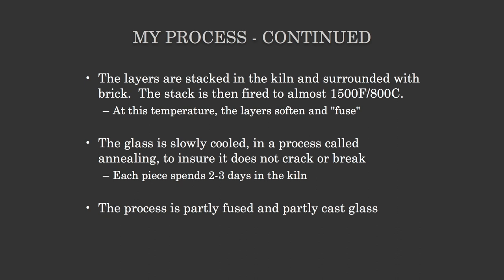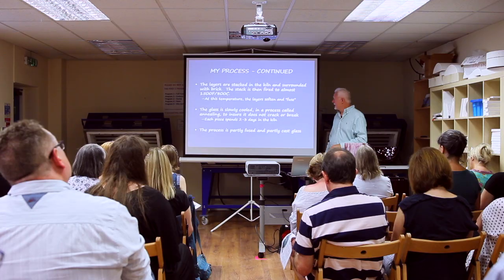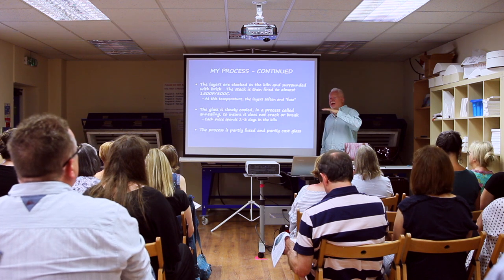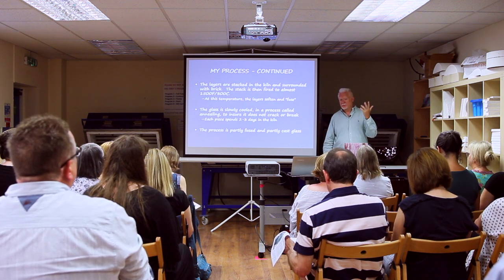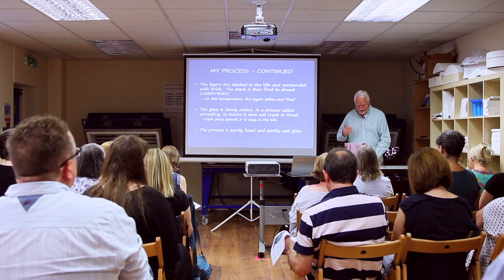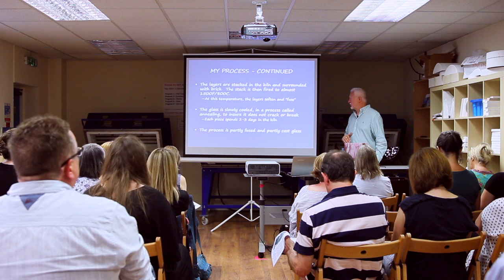Because at this point, I heat it up to 800 degrees Celsius, and at that point, the glass melts to the consistency of honey. It's a very thick liquid, really. And at that point, all the layers fuse together. So this piece, even though it was nine layers of glass, it's a single layer of glass now because all that glass is melted together. And then once it reaches that temperature, the glass is very slowly cooled through a process called annealing. And I think most of you in the room know that is just a process to keep the glass from cracking or breaking. But in very thick work, the annealing process is very long. So the final firing for these pieces takes 2 to 3 days.